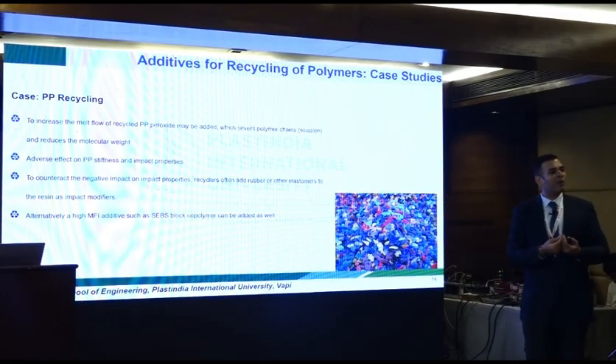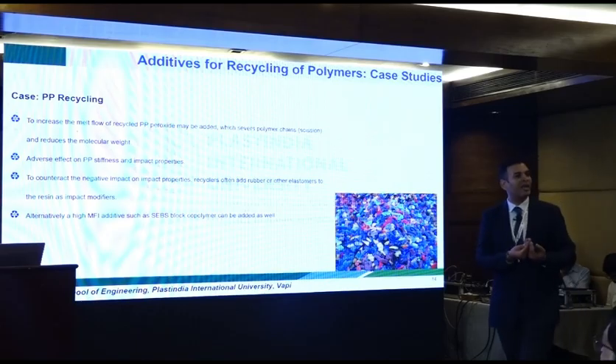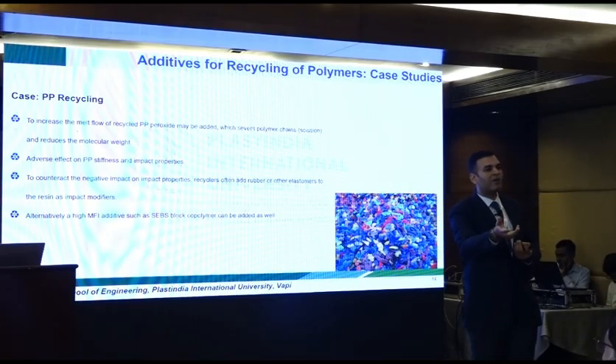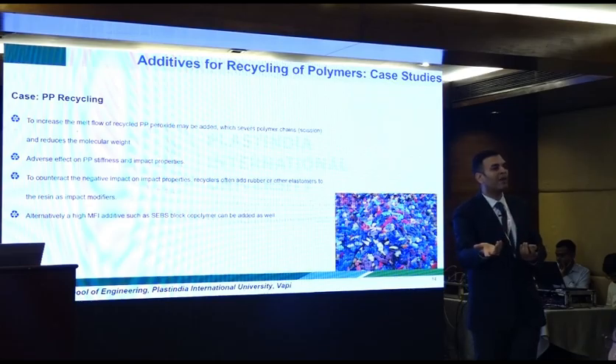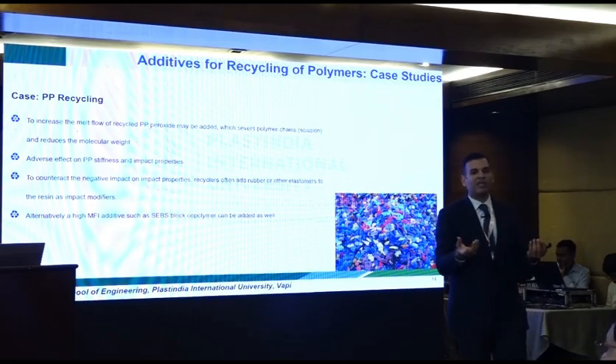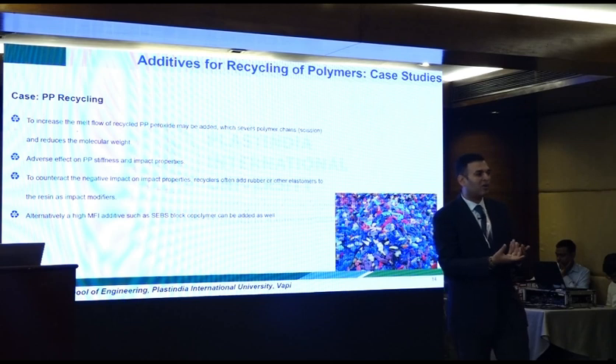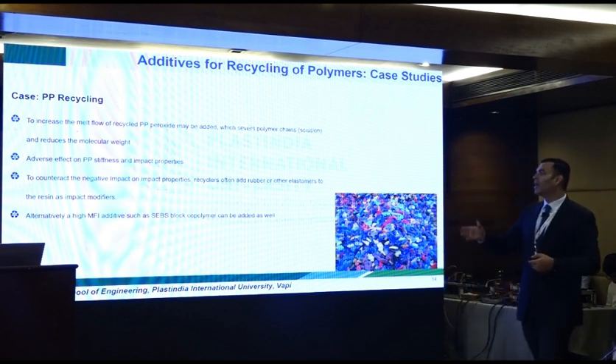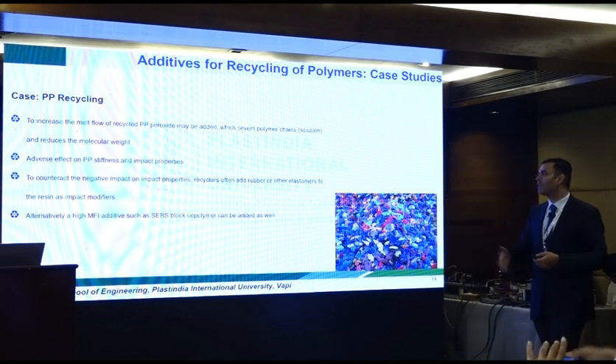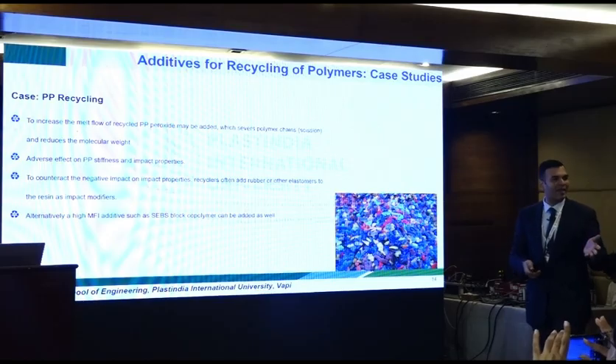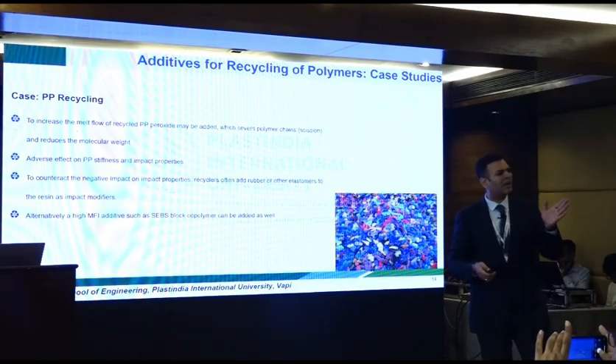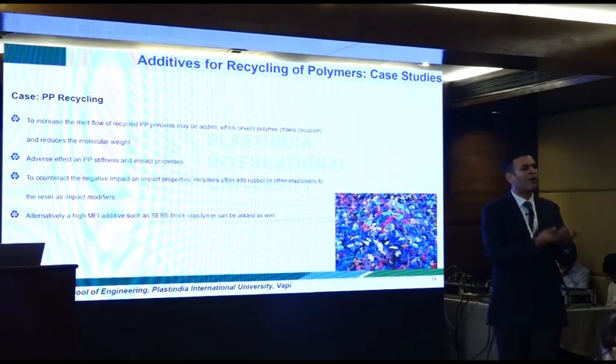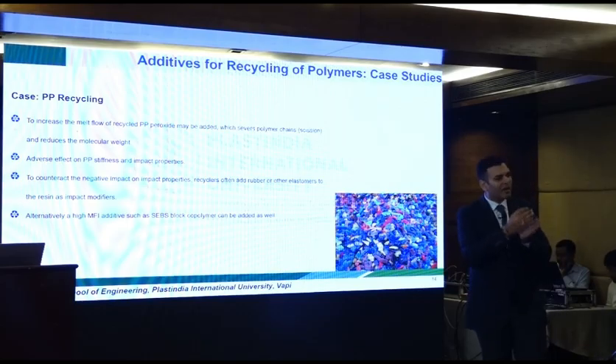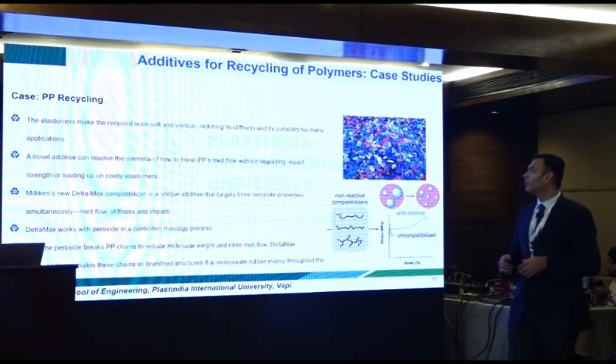So impact properties और stiffness पे अगर adverse effect आ रहा है, you add a compatibilizer into it or you add a rubber based compound into it which works as an impact modifier. The only thing that you will need to be sure is whether it meets the cost requirements or not. Alternatively, a high MFI additive like SEBS block copolymer can be added as well. So there are materials जिनका MFI खुद का ही high है. So add a block copolymer, it has certain amount of content of styrene in it and it will help you increase the flow rate of the material.